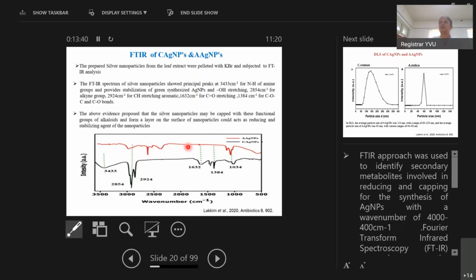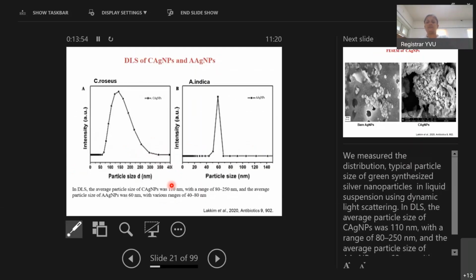This red one represents the Azadirachta indica silver nanoparticles, and the black one represents the Catharanthus roseus silver nanoparticles, with the functional groups present in the leaf extracts. After that, we measured the size distribution of the green synthesized silver nanoparticles through the dynamic light scattering technique. For Catharanthus roseus silver nanoparticles, we observed a sharp peak at 110 nanometers, ranging from 80 to 250 nanometers, and in Azadirachta indica, a sharp peak at 60 nanometers, ranging from 40 to 80 nanometers. This is the size distribution of both green synthesized silver nanoparticles.